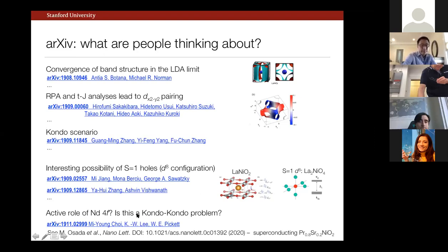And finally, there's an interesting additional problem in that the majority of the early electronic structure calculations have essentially dealt with all of the 4f states in the core, right? It's quite computationally expensive to deal with, and is in most cases fairly electronically inert. However, it is obviously a possibility. Namely, is there the possibility that you have direct hybridization of the neodymium 4f states with the chemical potential? So this is just my cheeky way of putting this. Is this a Kondo-Kondo problem? And at least one early paper on this was also coming from Warren Pickett on this issue.